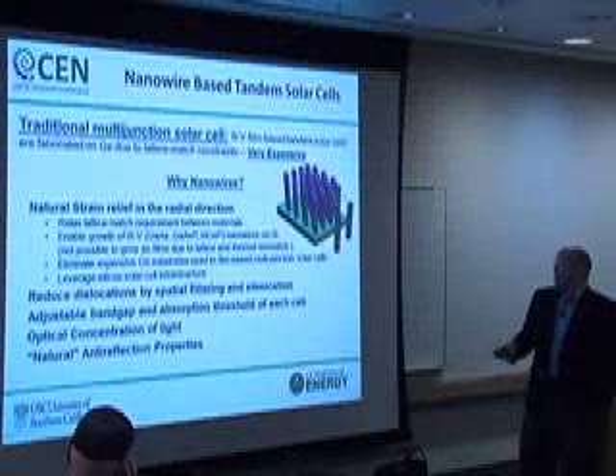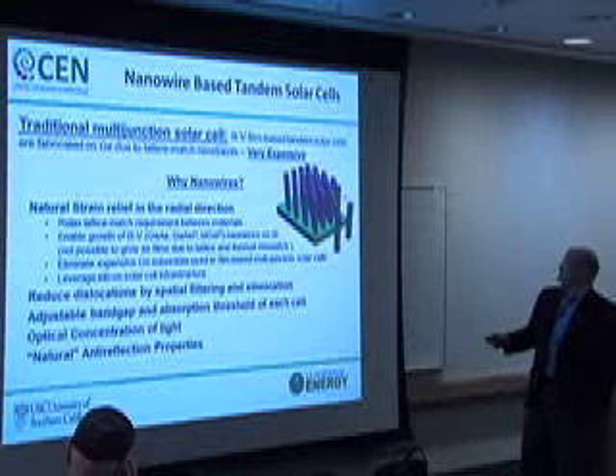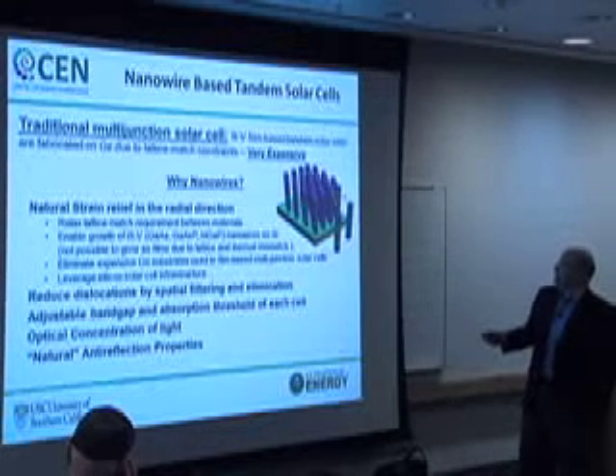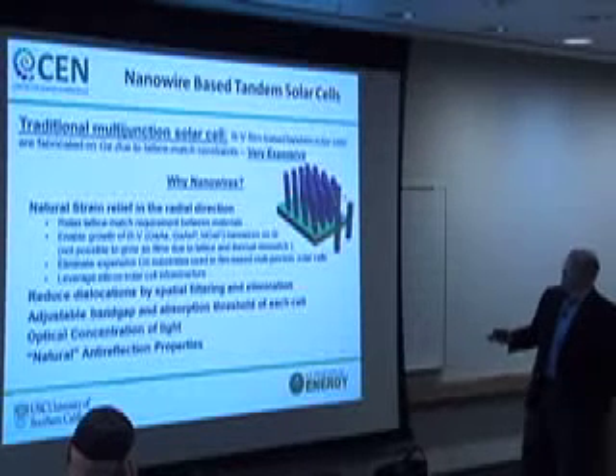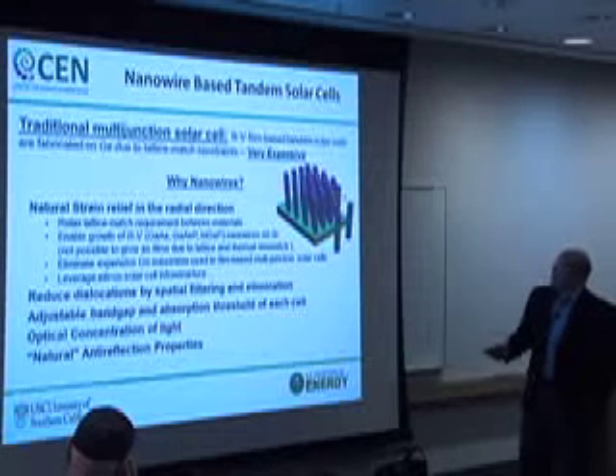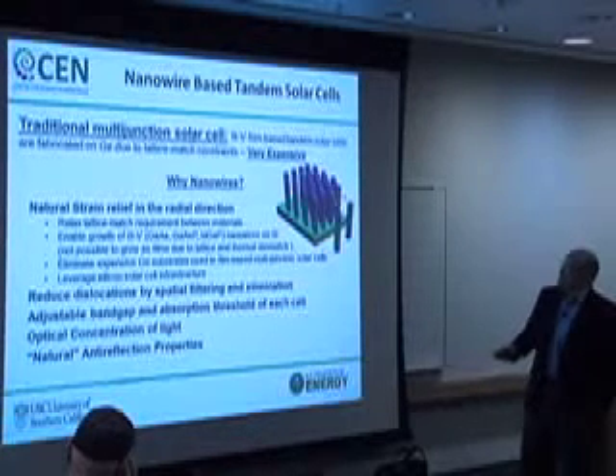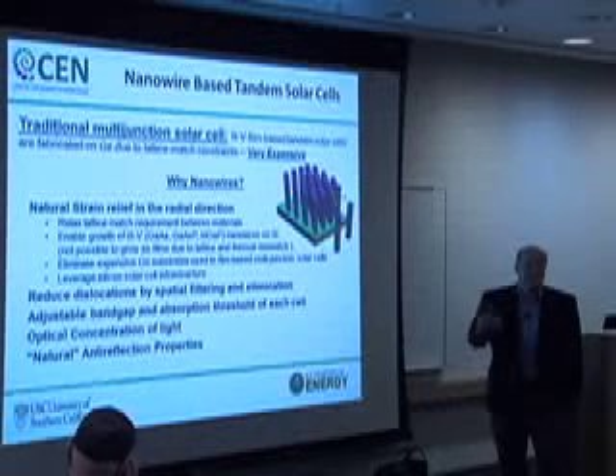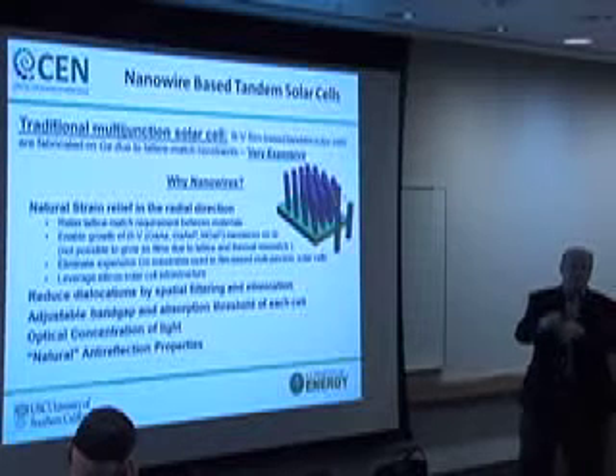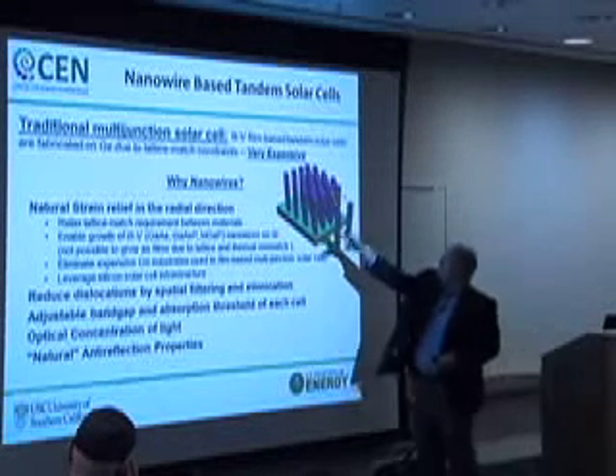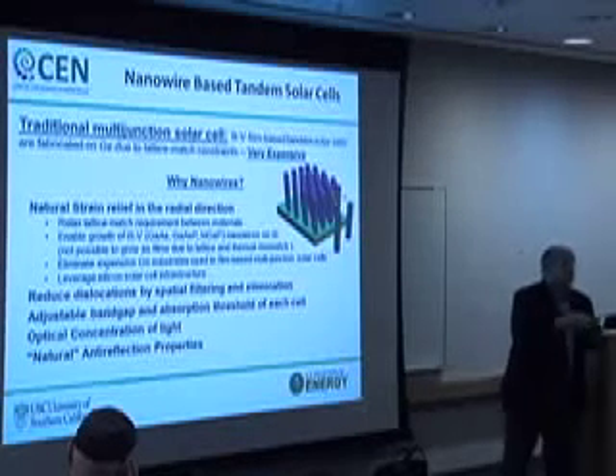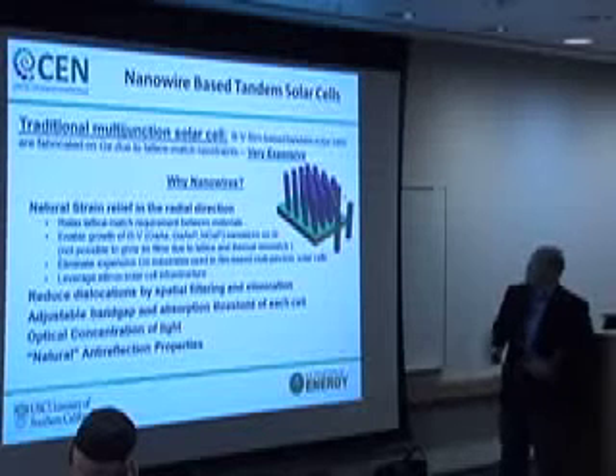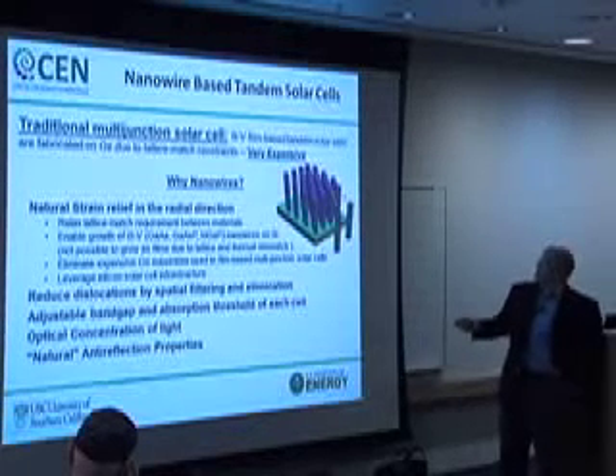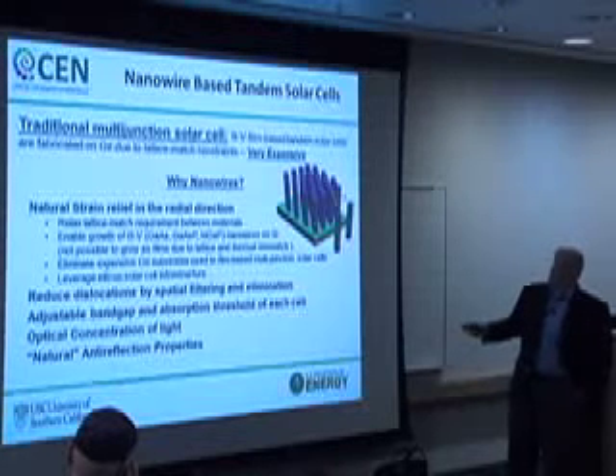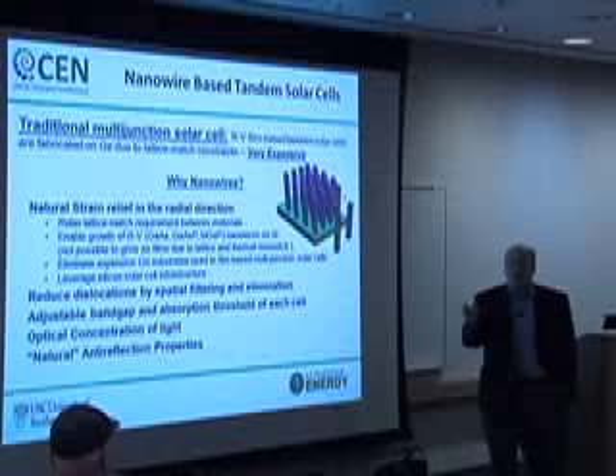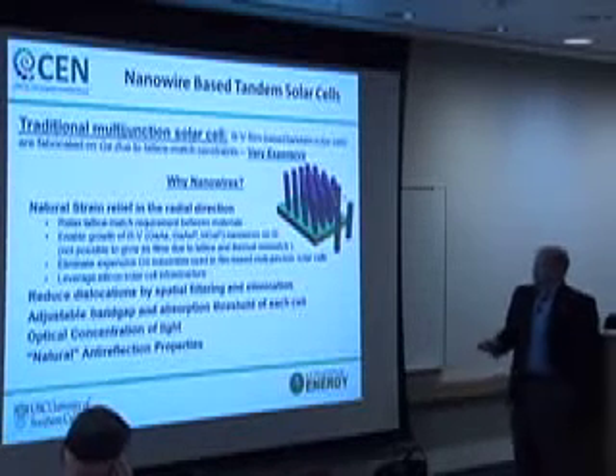So the other idea is that if we could accomplish this and say use a silicon single crystal substrate here, we could leverage that technology, which is already well developed. Now the advantages of nanowires is that the dislocations within the nanowires are either eliminated or reduced by two effects. One is spatial filtering. If you're only covering 10% of the area here with nanowires, you will miss any dislocations that happen to be in the substrate, although in silicon that's not usually an issue. But in addition to that, the dislocations tend to bend over towards the sides of the nanowire as it grows and don't propagate all the way to the top of the nanorod.